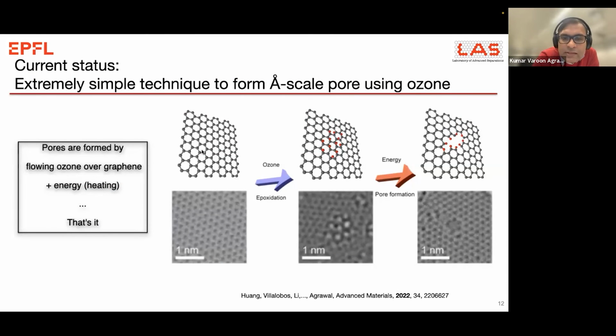It's not a problem. And then you can expose this to an oxidant. In our case, the oxidant is ozone. Why ozone? Because if you want to do this on a larger scale, ozone can be conveniently used. We can do this near room temperature. Ozone is very reactive towards graphene. 70 kilojoules per mole, the number that I talked about, is very accessible at room temperature. And then you make a graphene oxide kind of a structure on a single layer.